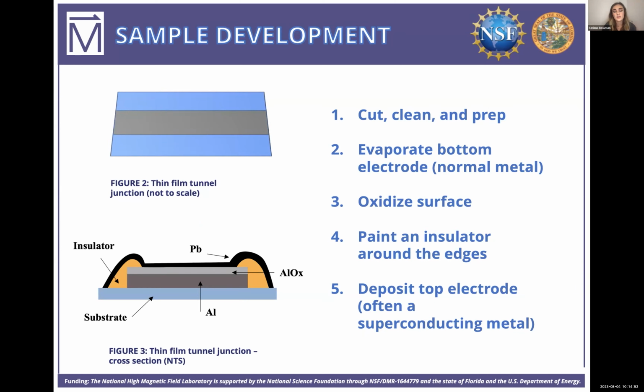And then I would oxidize the surface to create that insulating barrier, and also paint the edges with an insulator to make sure that there's no points of contact with the top electrode, which I then deposited. And these metals are evaporated in a vacuum chamber. So the last thing is evaporating lead, which is a superconductor, on top. After this is done, I was able to attach wires and take measurements of the sample.